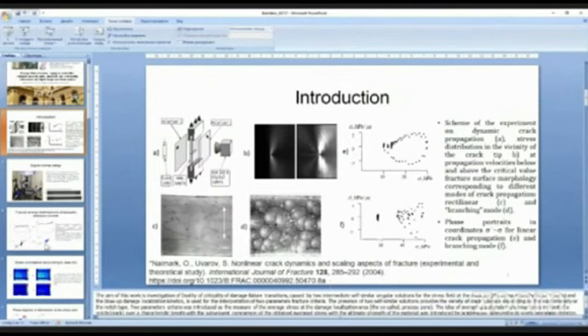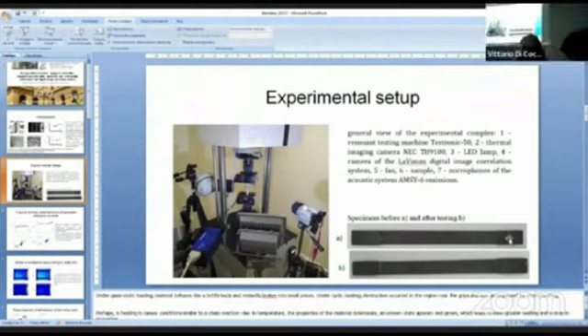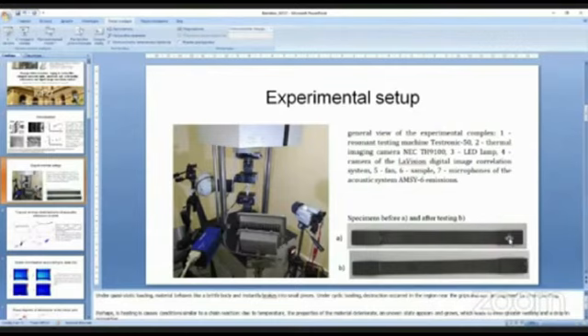In our work, we investigated composites. The first step was with unidirectional composite materials. We studied them under quasi-static and cyclic loading in the block loading mode with a gradual increase in amplitude. Realization of experimental program analyzing the acoustic emission. You can see the gauge here. And with digital image correlation analysis. The system is here in blue.